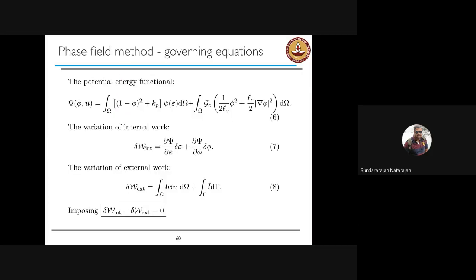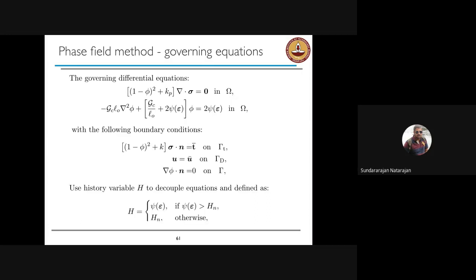So now the total potential energy can be written as given by equation 6, where the first term is the bulk energy, and the second term is the energy coming from the phase field. We follow the same procedure. We take the variation with respect to the strain and also the phase field variable. So now you have to keep in mind that we have to solve for the strain and also for this new variable called the phase field variable, which will dictate how the crack is going to evolve. And we follow the same variational framework. We end up with governing equations.